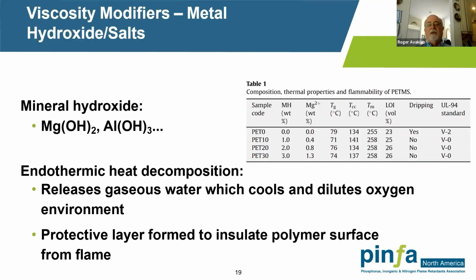Many times these materials are coated as well to help dispersion, but also to help them form a protective layer to insulate the burning material, holding it in, preventing dripping, but also smothering or preventing the access to more oxygen coming in, and also preventing the escape of flammable gaseous decomposition products. But again, typically large amounts are needed. And again, the effect of surface treatments to help the dispersion, as well as this drip suppression, is also needed.